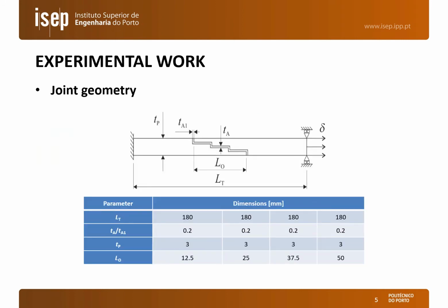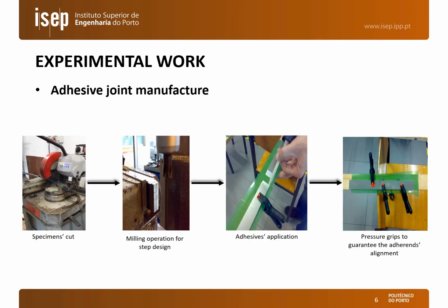The geometry presented in this figure was considered for the step-lap joints. Here we have as the main parameters for the joint LT, the joint length between grips, LO, the overlap length, TP, the adherend thickness, TA, the adhesive thickness, and TA1, the vertical adhesive thickness. As it is possible to see, we are going to make a step-lap joint with 3 steps. And we are going to consider overlap lengths between 12.5 and 50 millimeters.